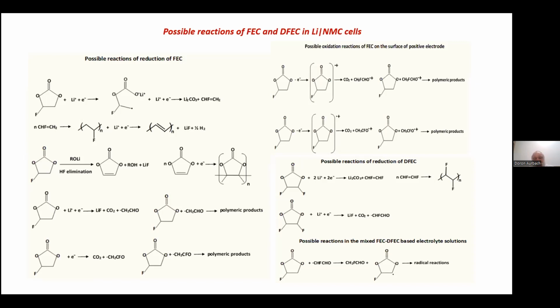And I don't want to go over this scheme, but you can find it in the literature in our papers. But because of the presence of fluoride we have reactions that form polymeric matrices. So we have polymeric matrices in which we have ionic compounds like lithium fluoride embedded. So we have matrices that contain oligomers and polymeric species. This gives the flexibility, and we have inorganic species, ionic lithium compounds that maintain the good mobility of lithium ion through the surface film. So we have here complex surface chemistry with a lot of options, thanks to the fluorine atom.